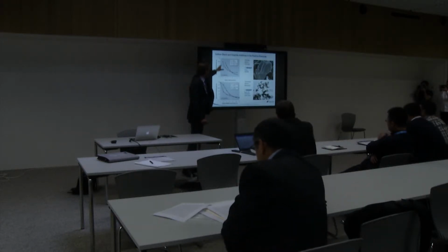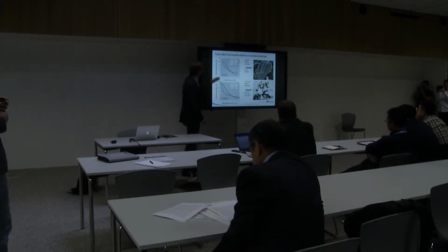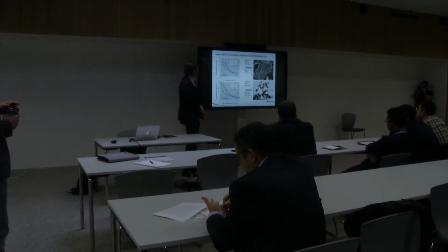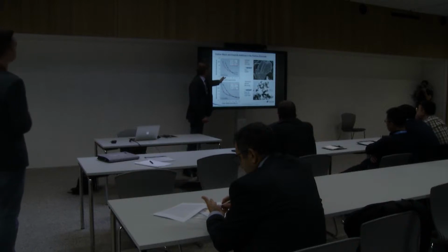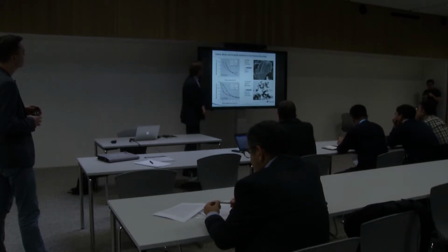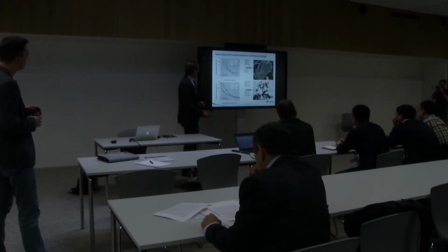What you can see here is a percolation threshold, where with increasing carbon amount, the resistivity percolates from a high resistivity level to a lower resistivity level. With carbon black, this critical volume fraction, where the percolation threshold occurs, happens at a lower carbon amount versus graphite, whereas with graphite we can reach lower ultimate resistivity levels when increasing the carbon amount to a higher level. And this is the same in LCO and LFP.